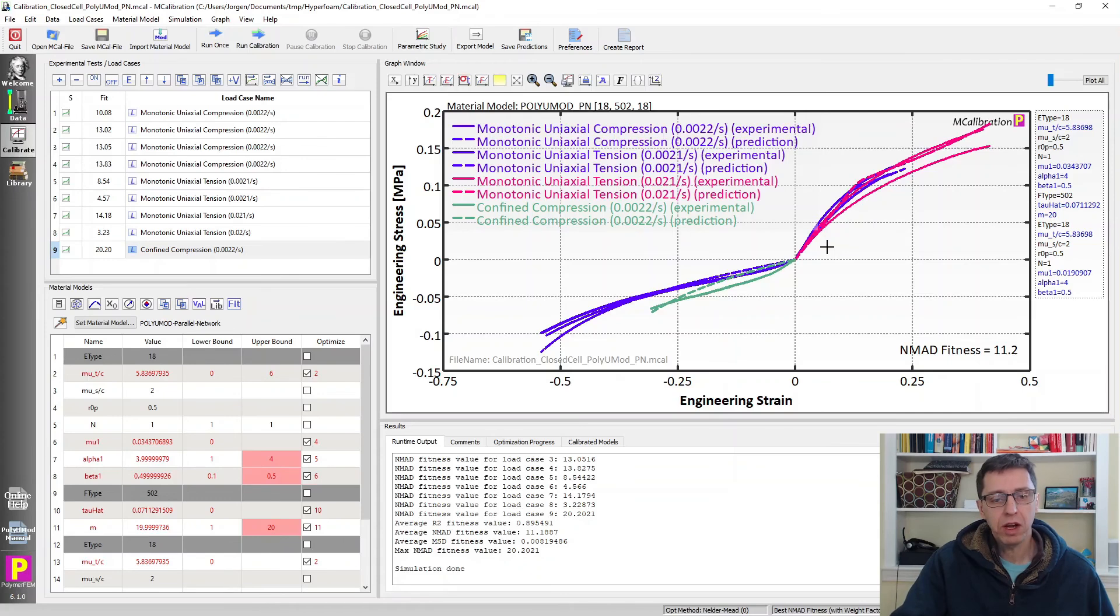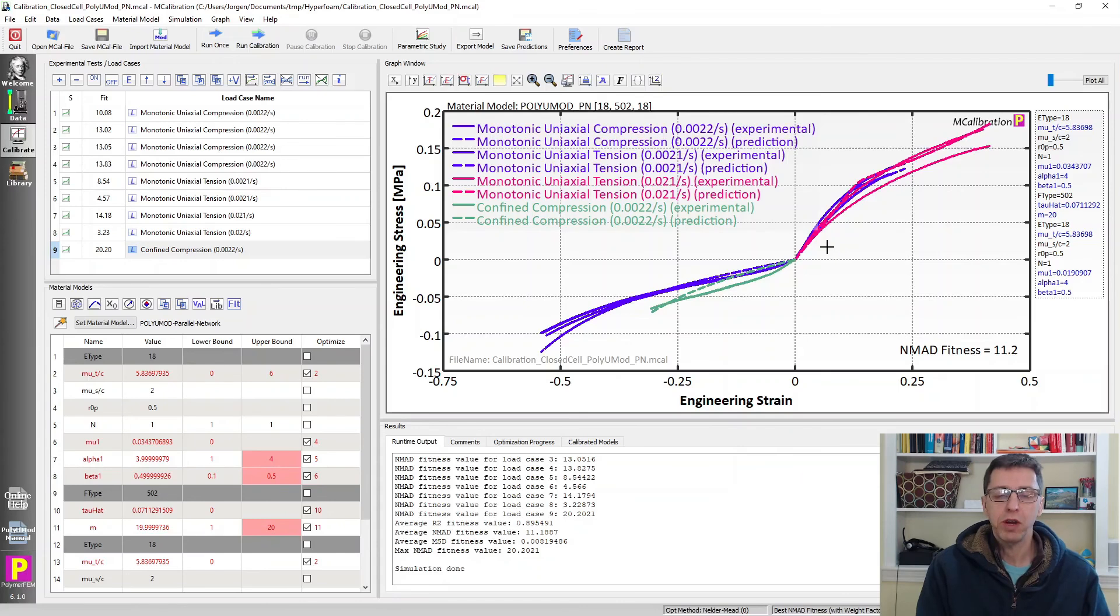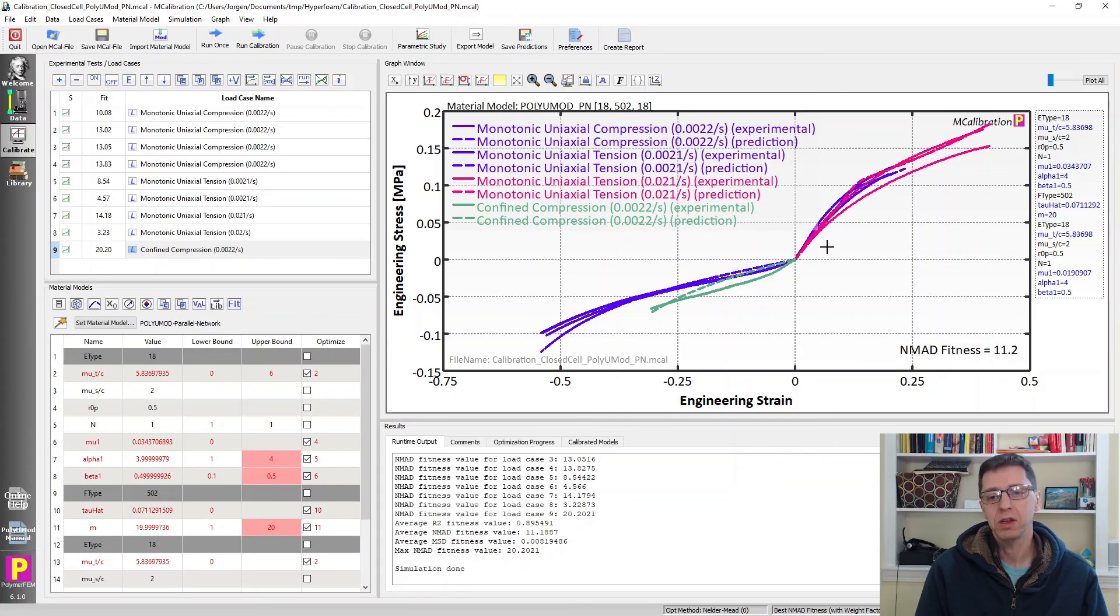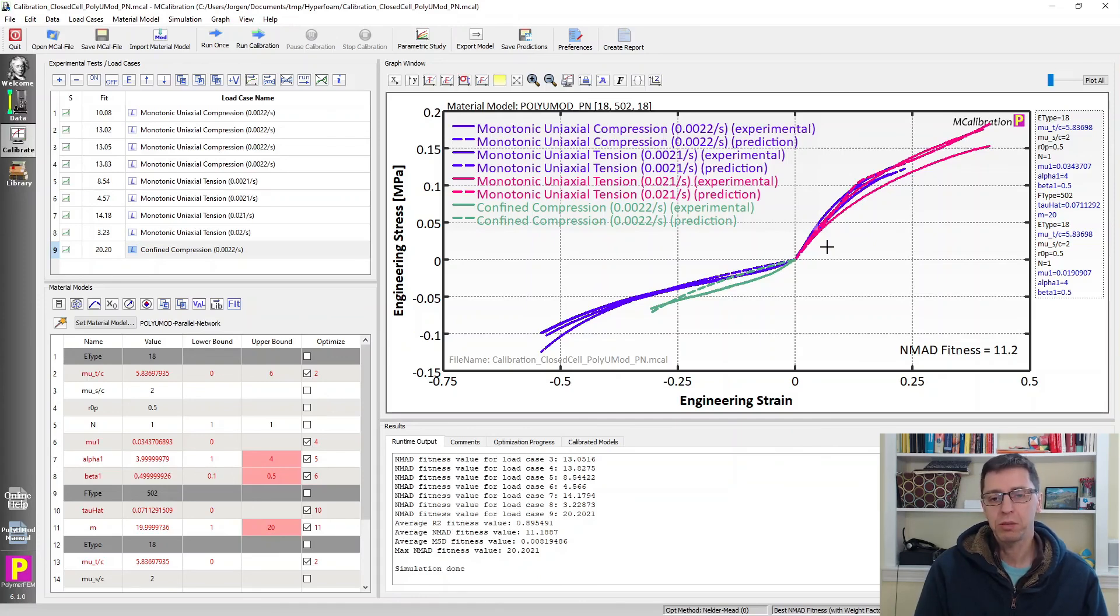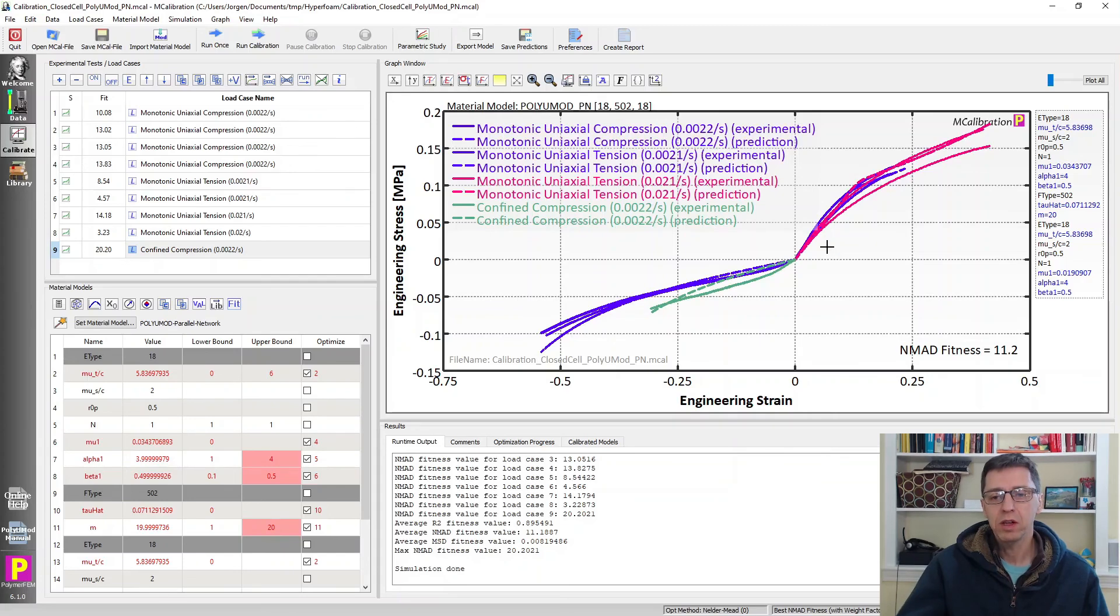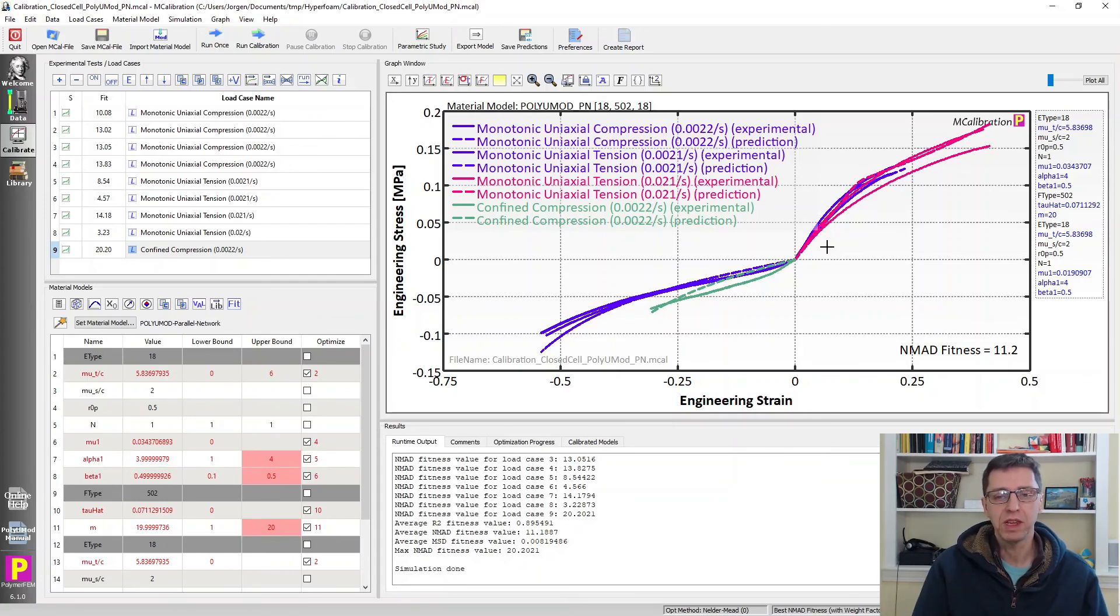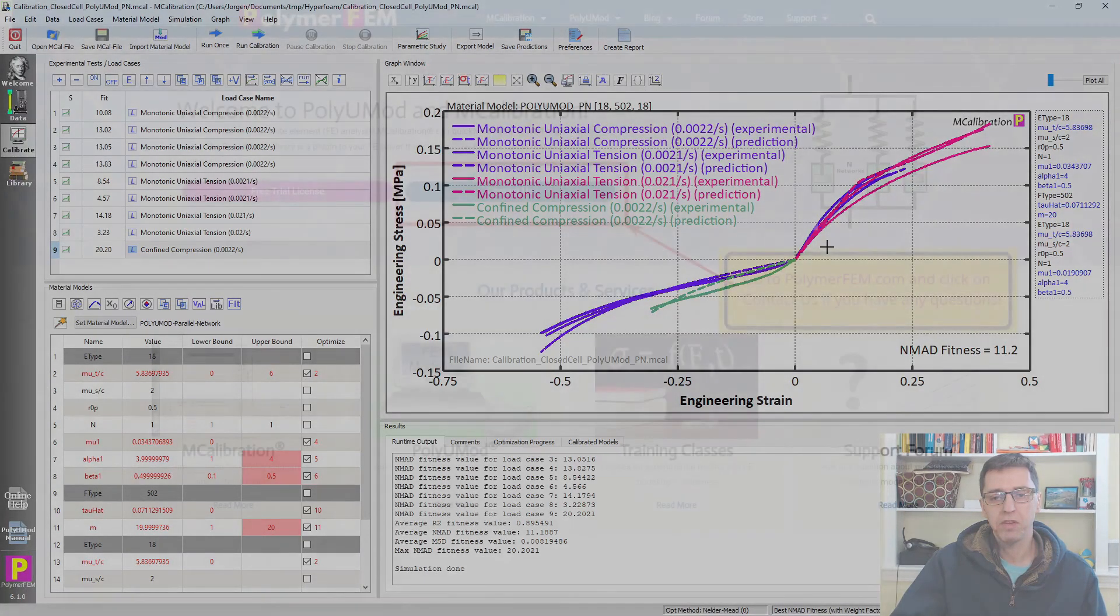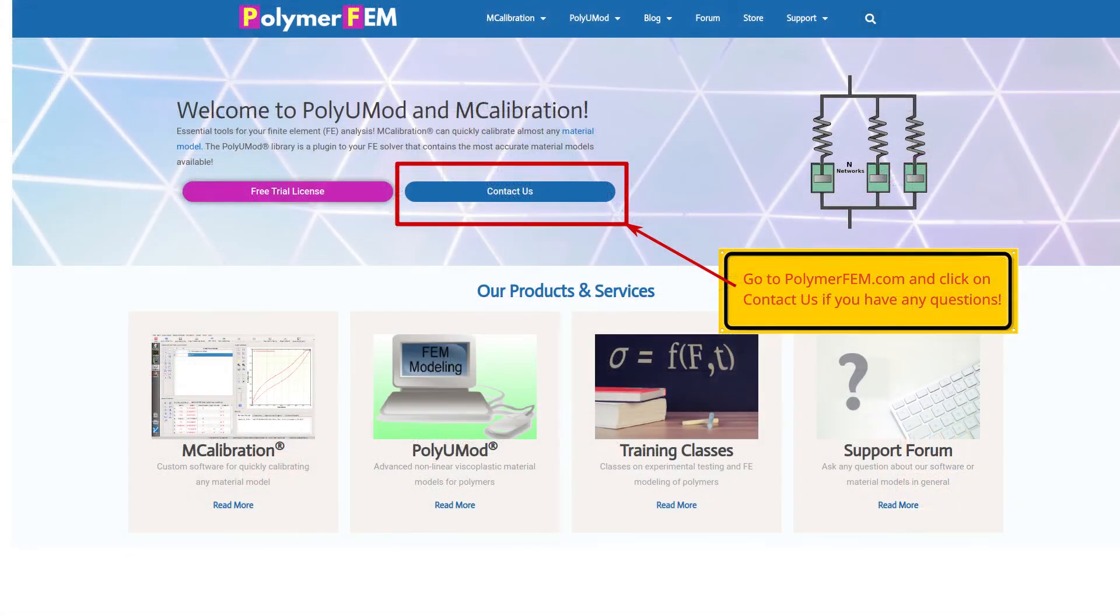So that's really all I wanted to show here about these hyperfoam models. They work really well. They're very quick to use in real simulations, but they do require two things. This is the final comment here. First, you need a very substantial amount of experimental data. You need tension, you need compressions typically. I would prefer shear, perhaps biaxial. You need a lot of data of different kinds to make sure that your model is stable and accurate and unique for the particular foam you're interested in. So that's the first thing. The second thing is you need to be a little careful when you calibrate it. Think about which parameters should be positive, which should be negative. And I think I tried to cover that here. So with that, I hope this was useful for you, and head over to polymerfem.com if you have any questions. Thanks.